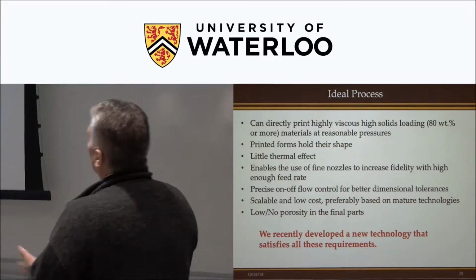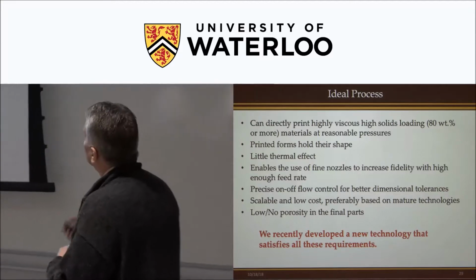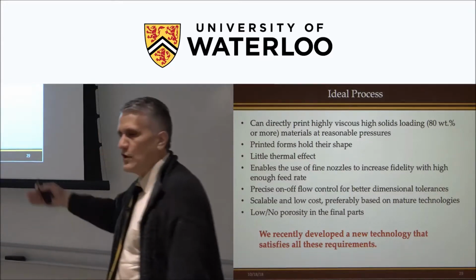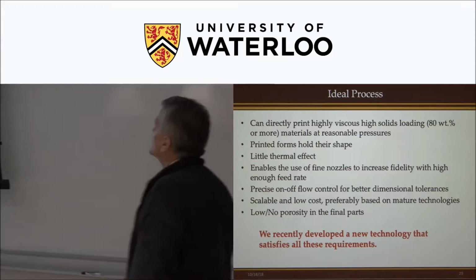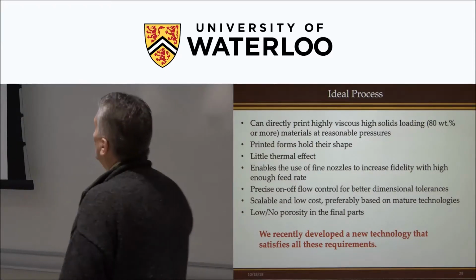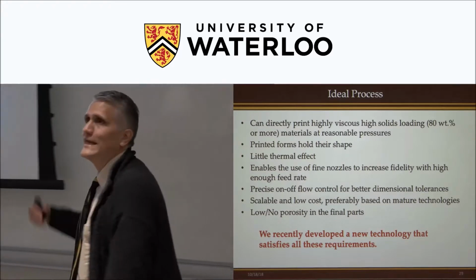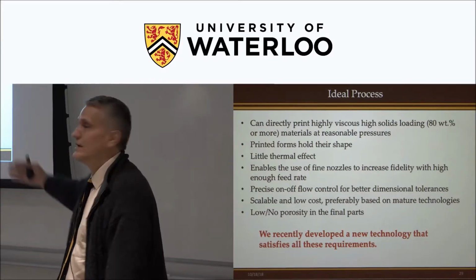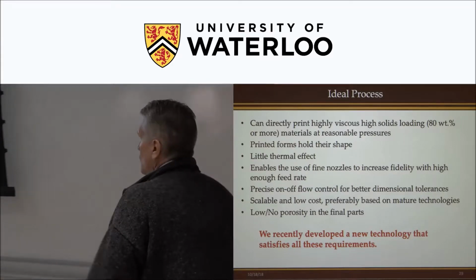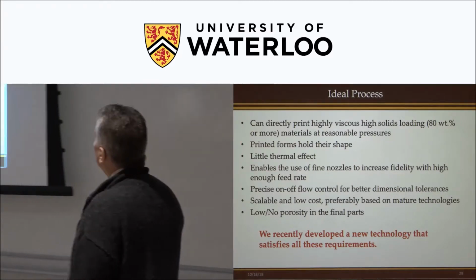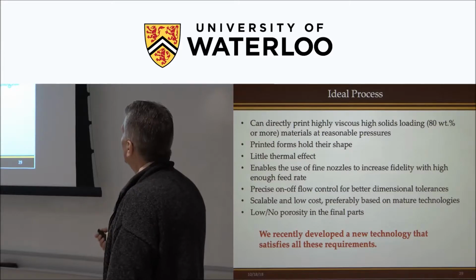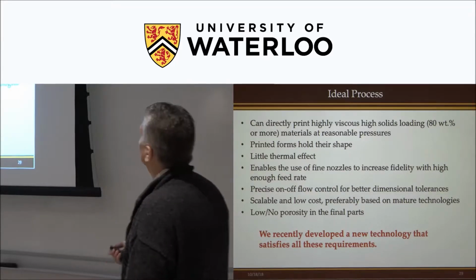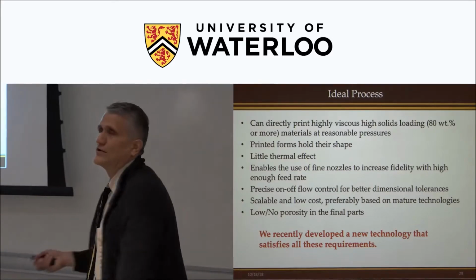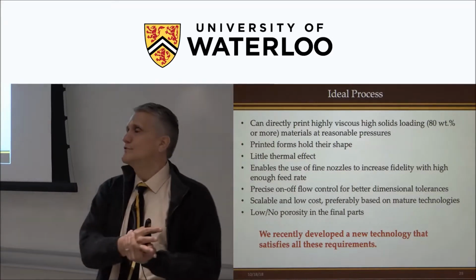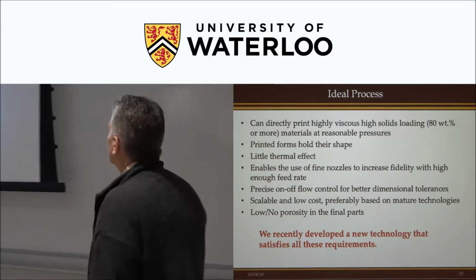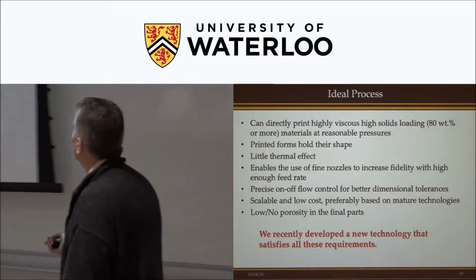So this is kind of the ideal thing. Ideally, we'd like to be able to go to at least 80%, certainly higher. High solids loading for solid propellants are like 88, 90%. We want the printed form to hold its shape. We want little thermal effect because we don't want to heat these materials up because they're propellants, right? They'll ignite. We want to be able to precisely turn the flow on and off to control dimensional tolerances. We want it to be scalable, low cost. We want low to no porosity in the final parts. If a propellant has porosity, the flame's going to get into those small gaps, pressurize, open up cracks, and then again, it's an explosive. It's no longer a propellant or a rocket.